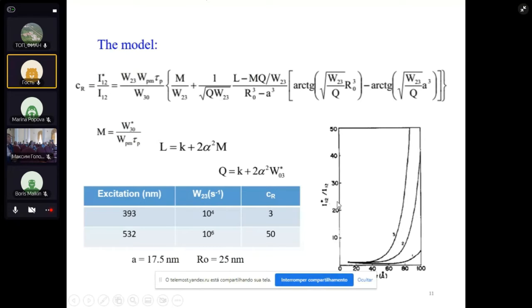So we were able to plot this as a function of the distance for different values of non-radiative decay. If we amplify this region here around 40 angstrom, we may see that, because of the competition involving energy transfer from the rare earth ions to the nanoparticles, we may even have quenching, a luminescence quenching region. We were able to describe this.